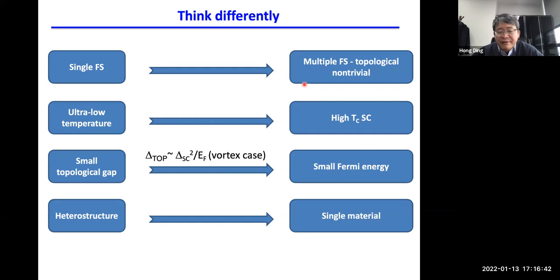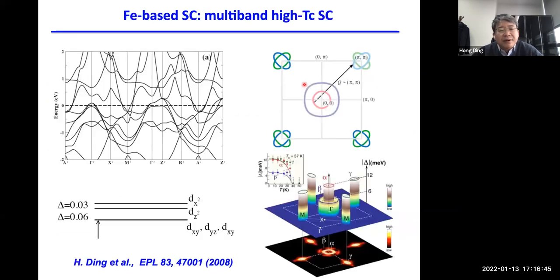And from the heterostructure, we have to think about a single material. So here comes iron-based superconductor, which is a multi-band high TC superconductor. As I showed here, many bands cross the EF, therefore quite a few, four or five Fermi surfaces, therefore the hole pocket and the electron pocket. And here is our early work to demonstrate this many Fermi surfaces with multiple superconducting gaps, which is essentially S wave, but it is Fermi surface dependent S wave.